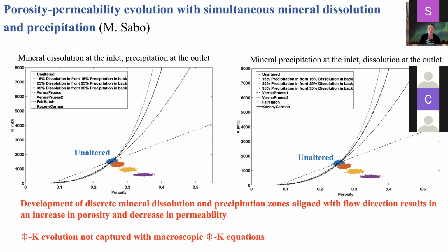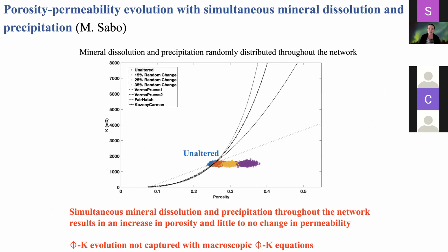We also considered, what if you have dissolution and precipitation happening randomly throughout the network? And in this case, you get an increase in porosity with really little change in permeability. So basically, even though you're constricting some of the pore throats, you're maintaining enough of the larger pore throats that your permeability is not impacted in this system. You also notice, though, this is not captured with our current means of estimating permeability evolution.